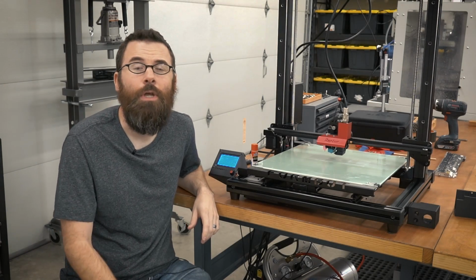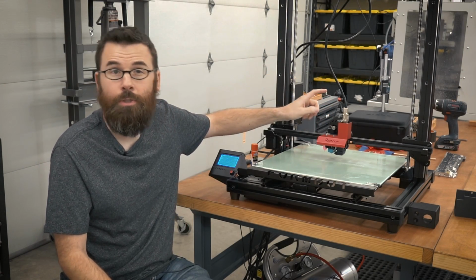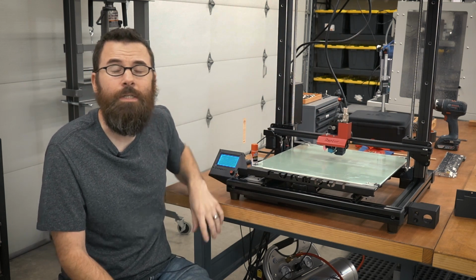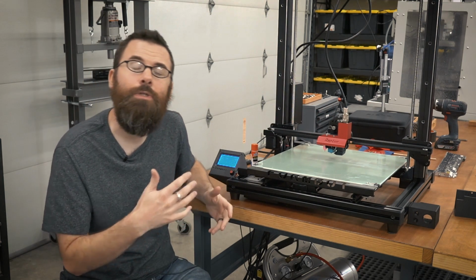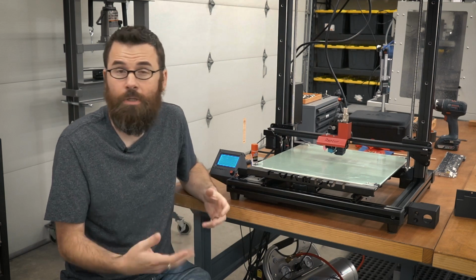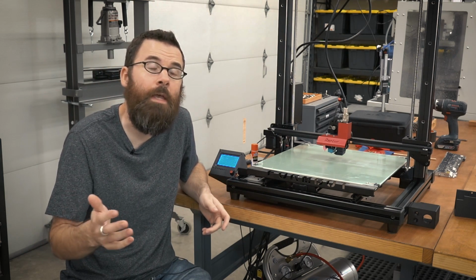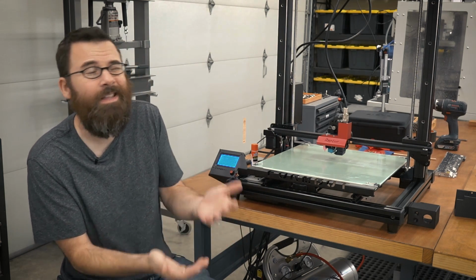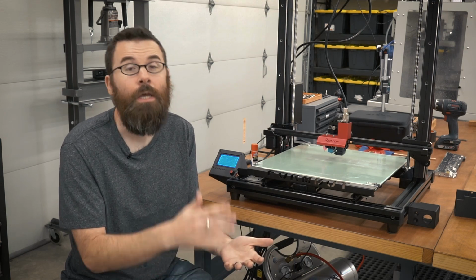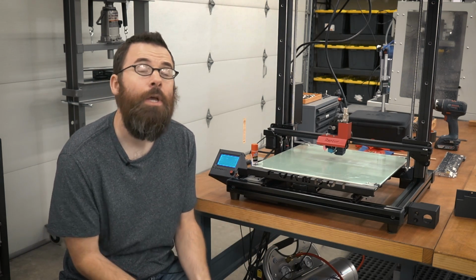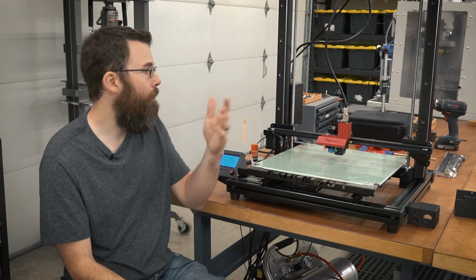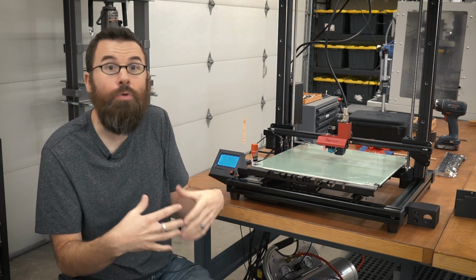The next thing that you need to know is the maximum temperature that your extruder can handle. Nylon-X needs to be printed somewhere between 250 and 260 degrees Celsius, which is pretty hot. It's a lot hotter than PLA, which can be printed at like 190 to 210, so there's a lot more heat there. You might need a bigger heater block, maybe your thermistor can't handle the temperature, who knows.